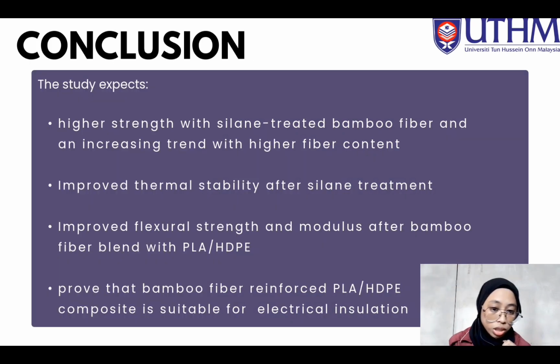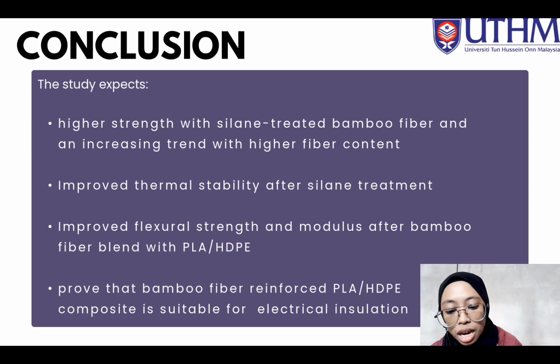For the conclusion, I will conclude that this study expects, firstly, higher strength with silane treated bamboo fiber and increasing strength with higher fiber content. Secondly, we expect that we can improve the thermal stability after silane treatment. And lastly, we expect that we can improve the flexural strength and modulus after the bamboo fiber is blended with PLA HDPE.